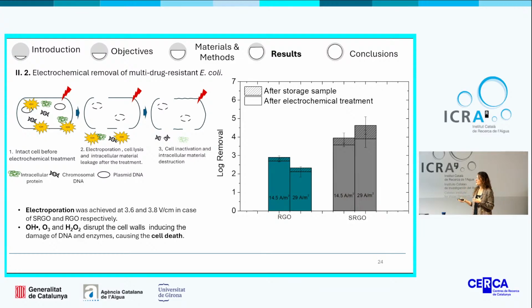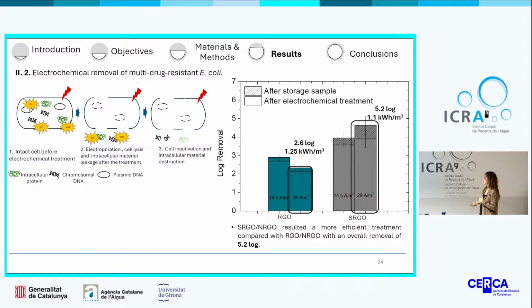But not only electroporation, also different oxidant species are participating in the inactivation of bacteria, since they can diffuse into the cell membrane and disrupt the cell walls, causing damage to the DNA and different enzymes, causing cell death. In this graph, we could see the log removal of the electrochemically treated samples, as well as the storage of the treated samples, because we would also like to study if a possible recovery or regrowth of bacteria was occurring. According to these results, not only were the bacteria not recovering, an additional elimination was observed, leading to a 5.2 log removal of this pathogen, compared with a lower removal in the case of reduced graphene oxide.